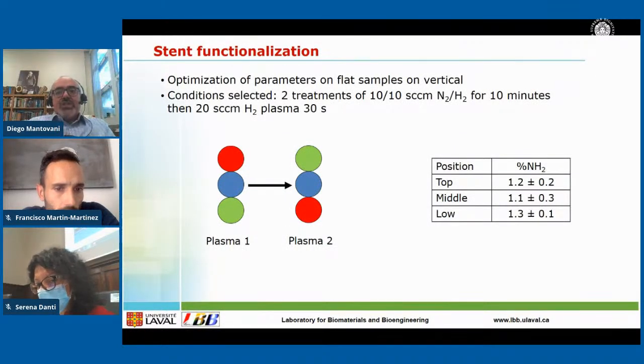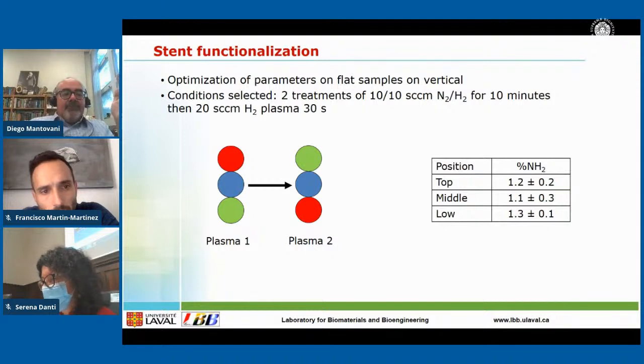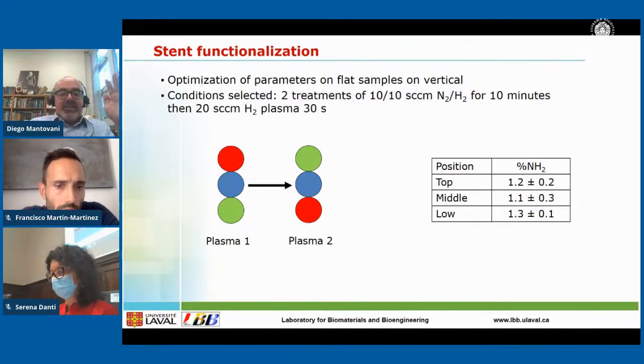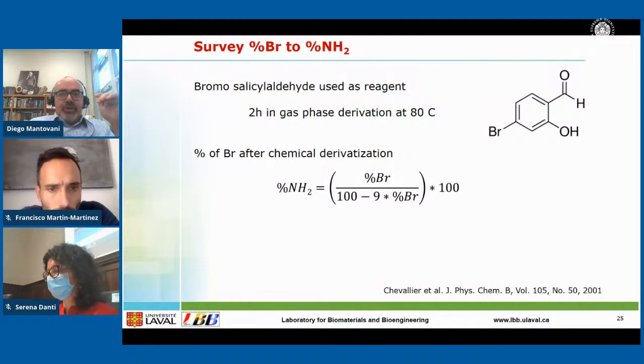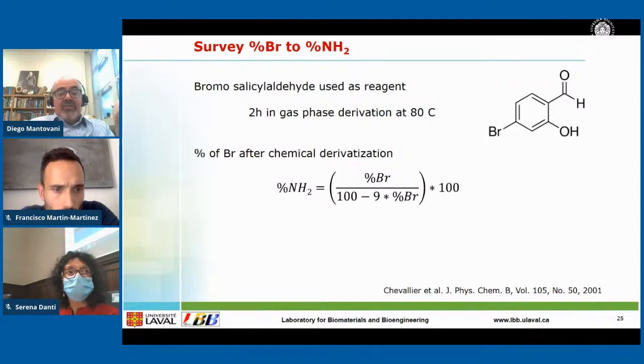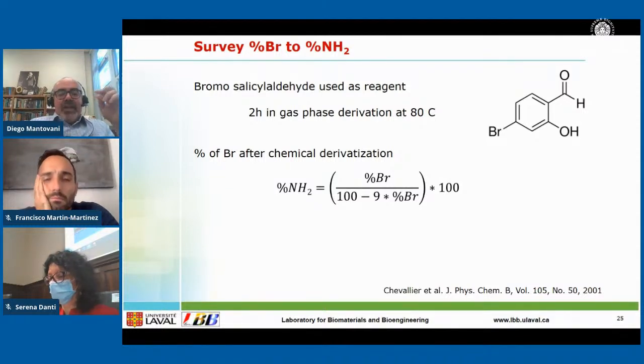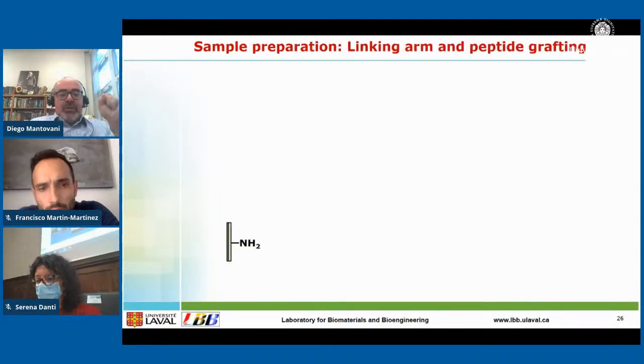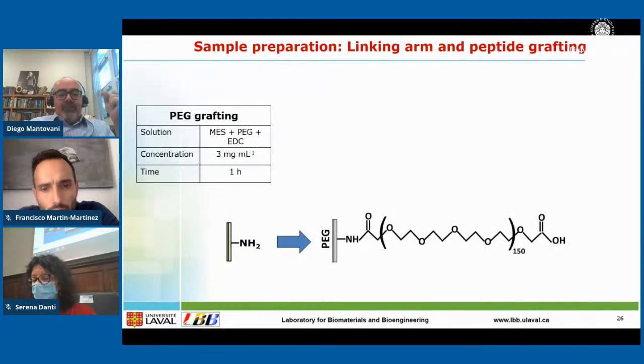So the homogeneity of the stent functionalization was assessed: the top part, the bottom part, and the central part, and basically this was confirmed. We used bromine in order to derivatize the amine group, to be able to assess the amination capacity of the process.